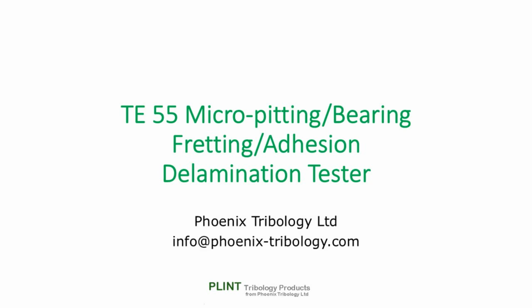Micropitting typically occurs in gears at a contact pressure of between 0.5 and 1.5 GPa and at slide roll ratios from approximately 0, the gear pitch point, and up to approximately 10%.